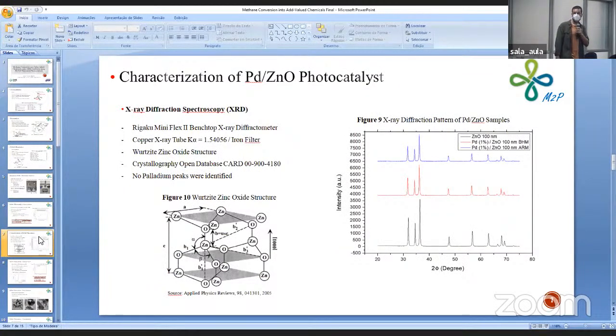We have then the X-ray diffraction analysis, and the diffractogram patterns can be seen in figure 9. The expected peaks related to the palladium nanoparticles at theta equal to 40, 46, and 68 were not identified, given the low content of metal in the samples. Besides that, the nano-size of the palladium particles can also broaden the diffractogram peaks related to the palladium nanoparticles, and thus they get lost in the background. Otherwise, we could identify the zinc oxide structure by XRD, and it is represented in figure 10, and its card in the Crystallography Open Database.